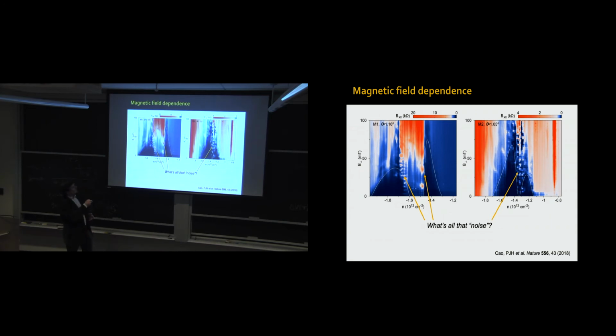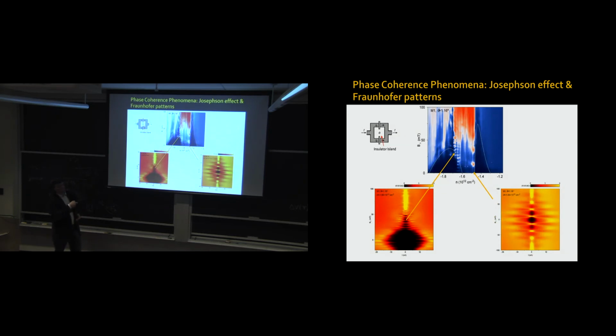So if you vary your chemical potential at these boundary regions, and measure the critical current as a function of perpendicular magnetic field, you get these Fraunhofer-like patterns which tell you there is Josephson interference through your superconductor, where there are a set of superconducting islands connected by insulating islands. Typically a couple of these islands dominate, giving you mostly a pattern which we can recreate with a single SQUID with either symmetric or asymmetric Josephson junctions. This is very interesting because it tells you there is phase coherence, a Josephson effect through your system, which confirms, if there was any doubt, that this is a two-dimensional superconductor.